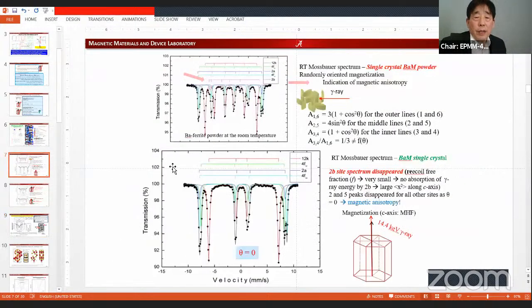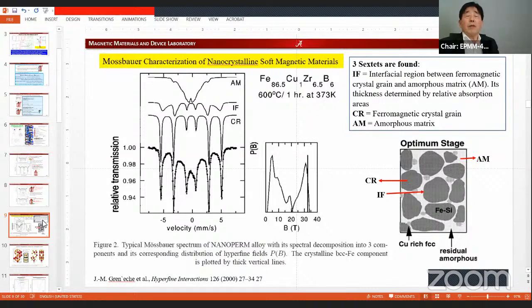Next one, you can apply Mössbauer spectroscopic characterization to nanocrystalline soft magnetic materials. This is a nanocrystalline soft magnetic material. You can characterize this into a core site, an interfacial site, and an amorphous matrix site. Once you analyze the Mössbauer spectra, you can identify the amorphous matrix right here, and this spectrum from the interface between the amorphous matrix and the crystallite, in this case iron silicon, and then this is the overall total spectrum here. So the Mössbauer characterization tool is fantastic for understanding nanocrystalline structured soft magnetic materials as well.